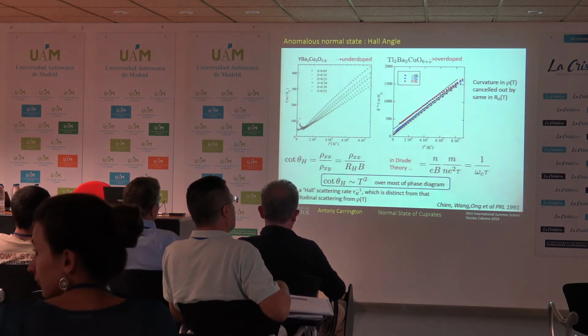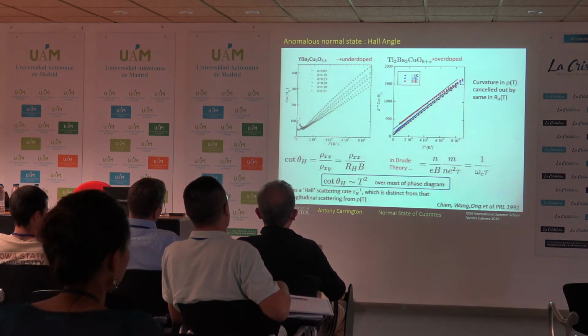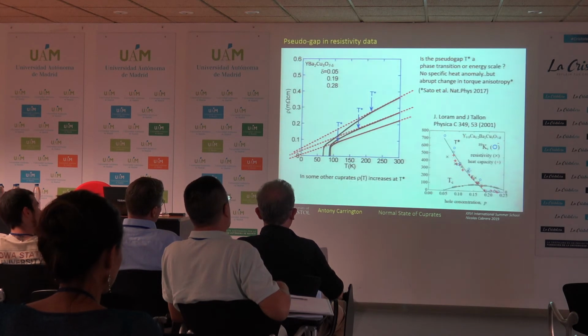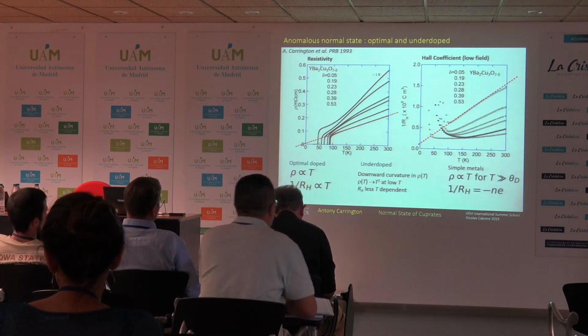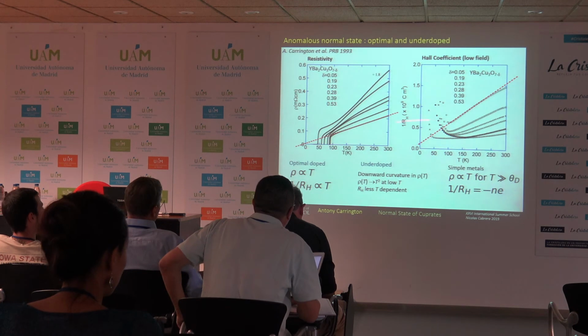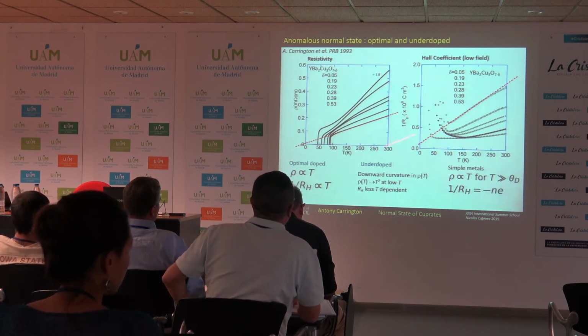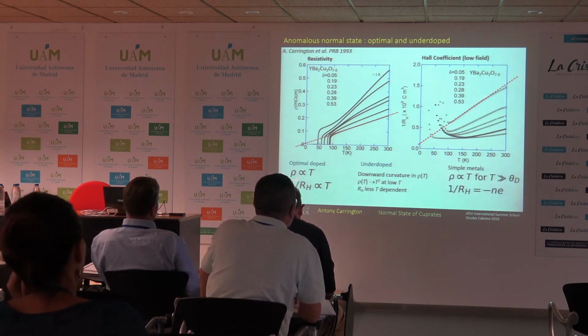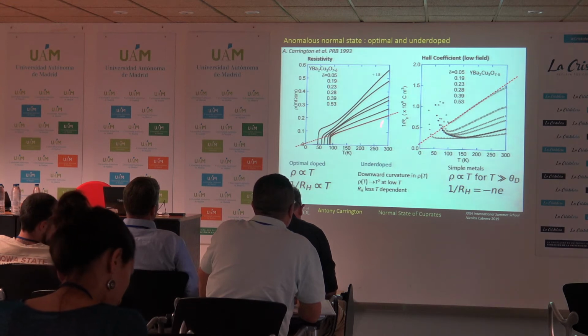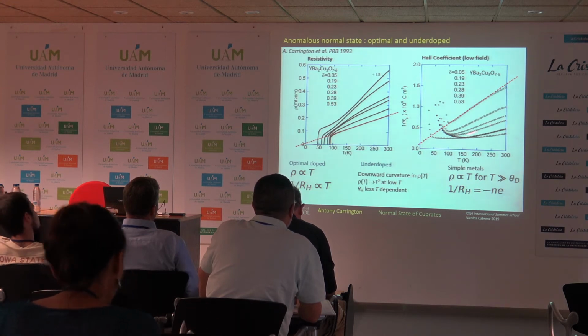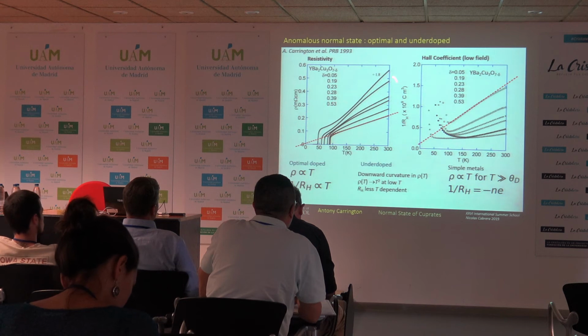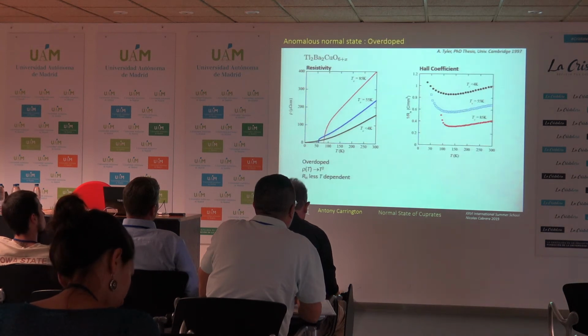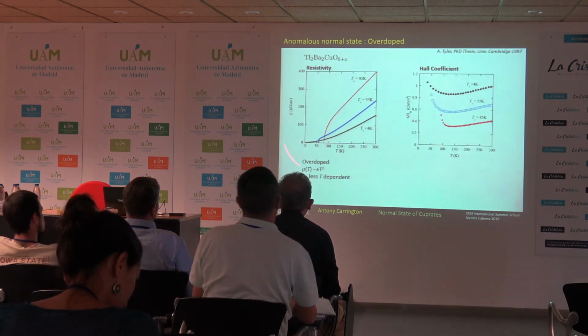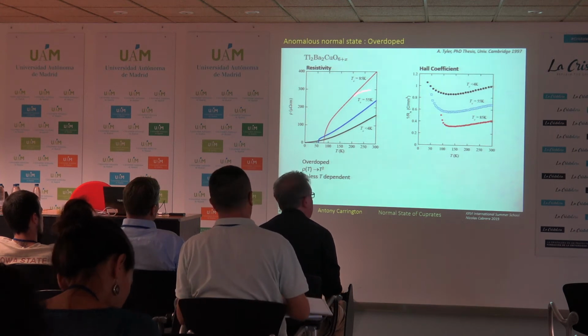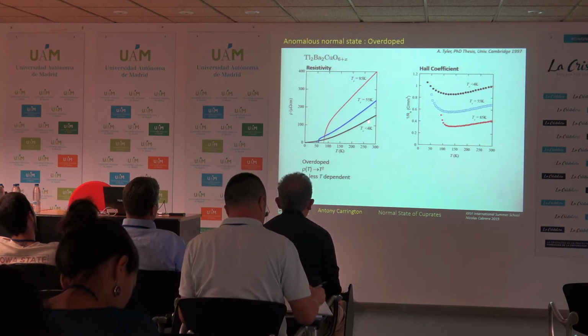Okay, so anyway, back to the Hall coefficient. Just to jump back a bit, I told you that there's this linear behavior of the resistivity, and there's also this linear behavior of the inverse Hall coefficient. But as I go underdoped, this gets less and less temperature dependent, and this develops a strange S shape. And indeed, also in the overdoped case, a similar thing happens. So this becomes T squared, and this becomes less temperature dependent.